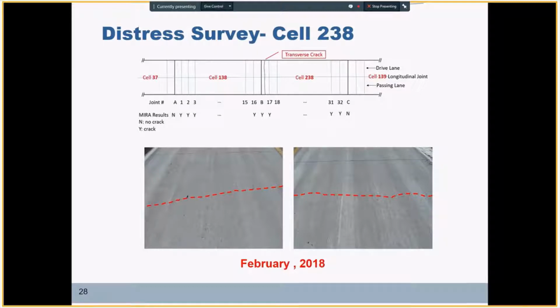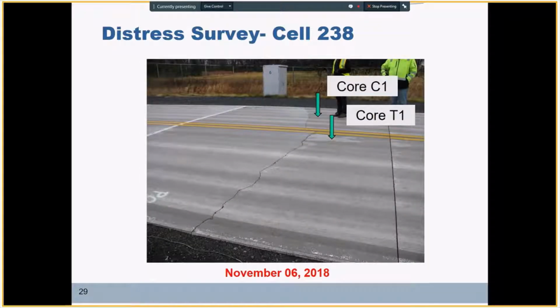We are trying to monitor the performance of the mixtures and pavements, considering distress surveys all the time. The first crack observed in these two cells was a transverse crack, fairly wide open, in cell 238 at the beginning of the concrete placement, first observed in February 2018.